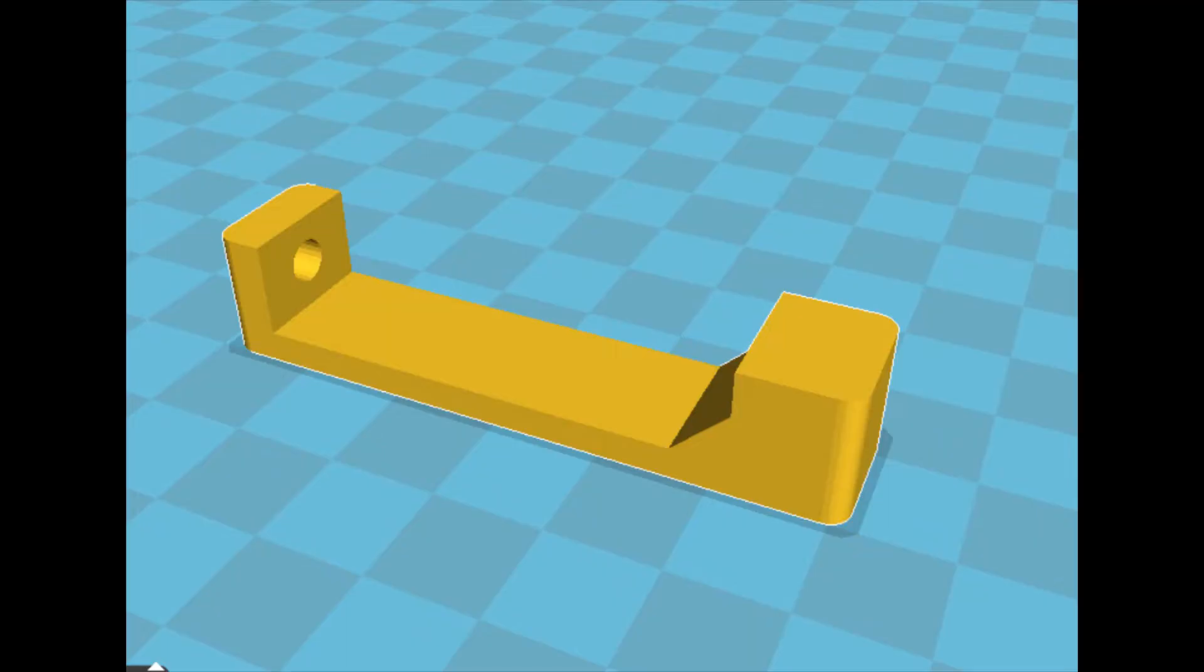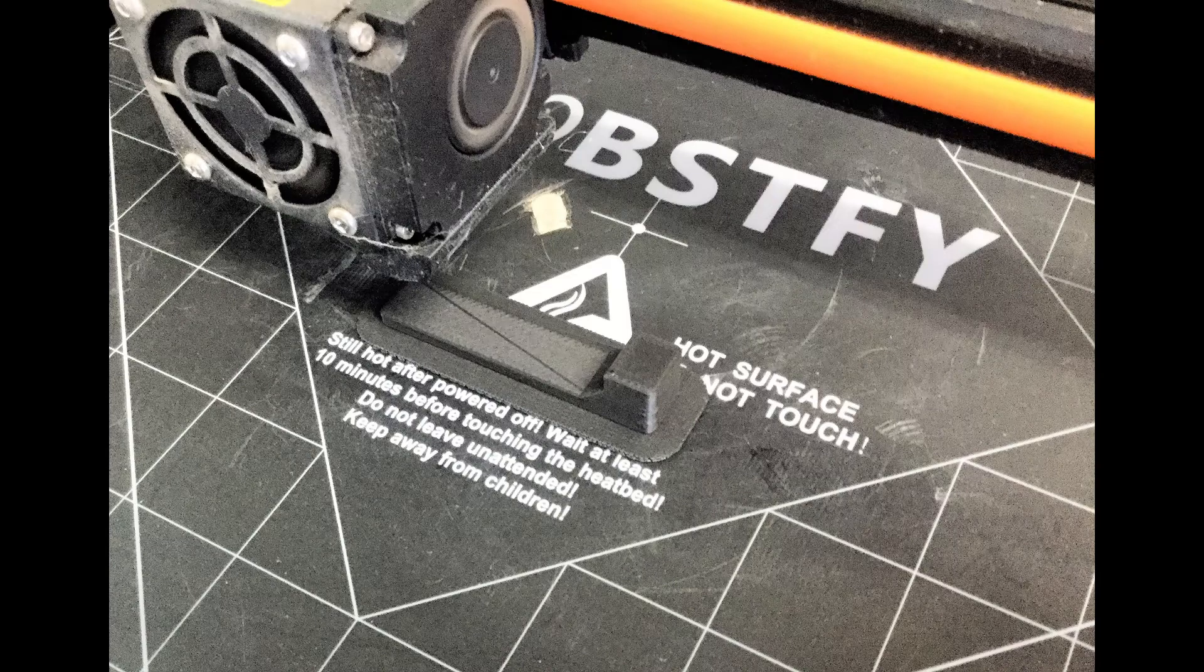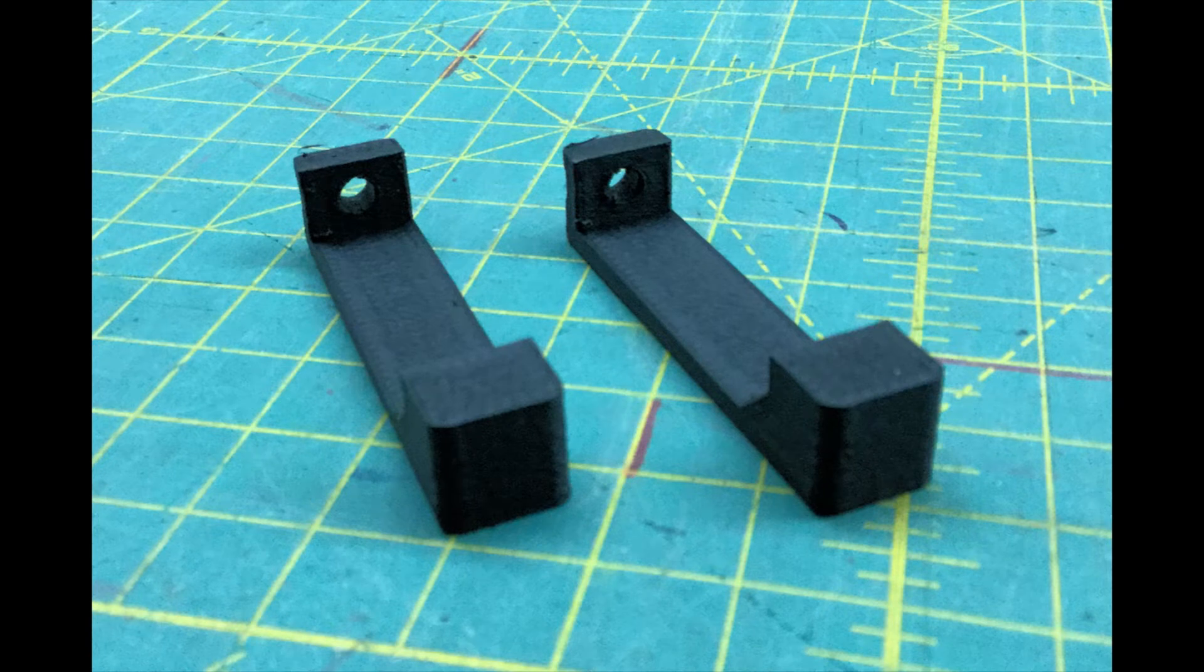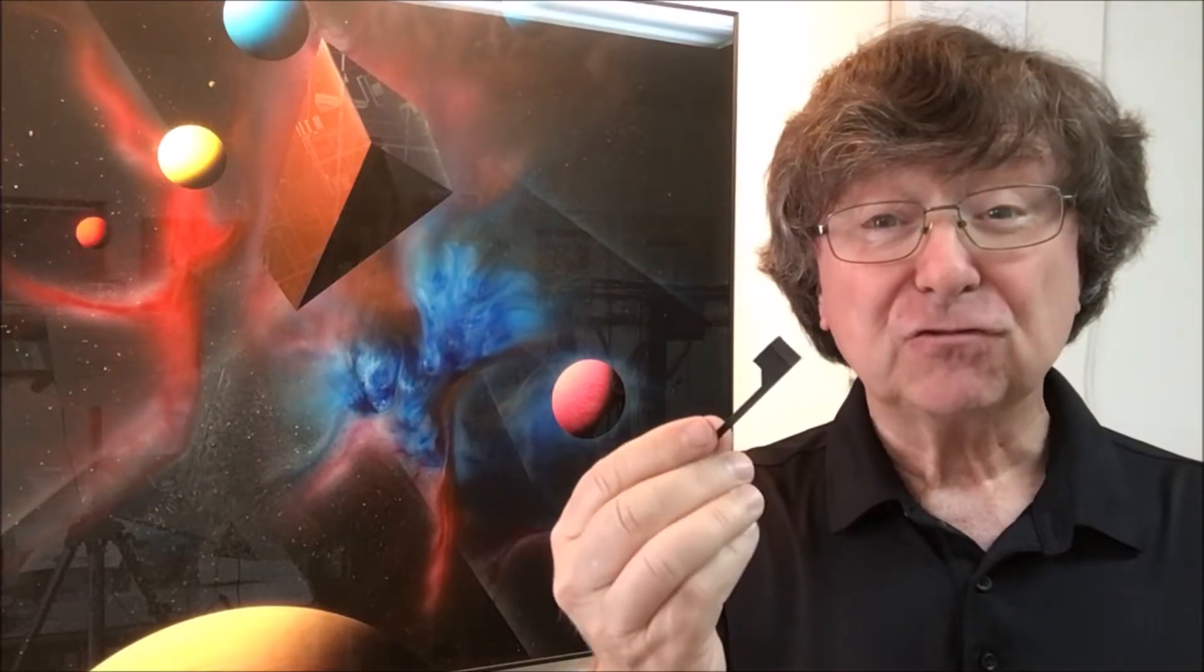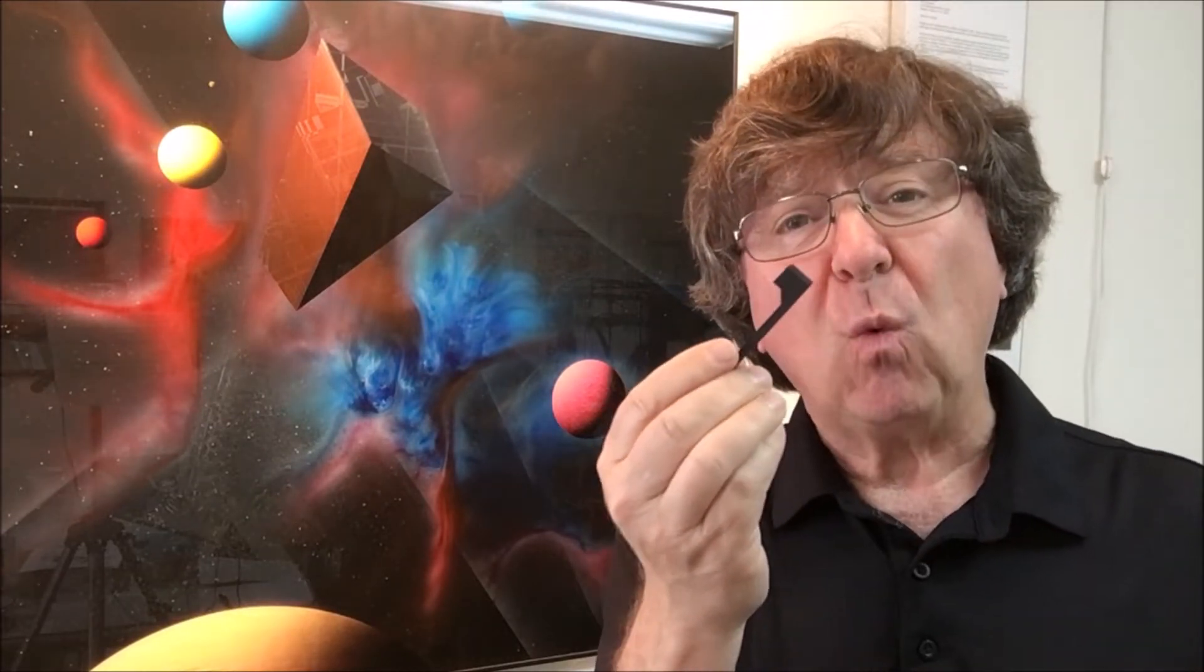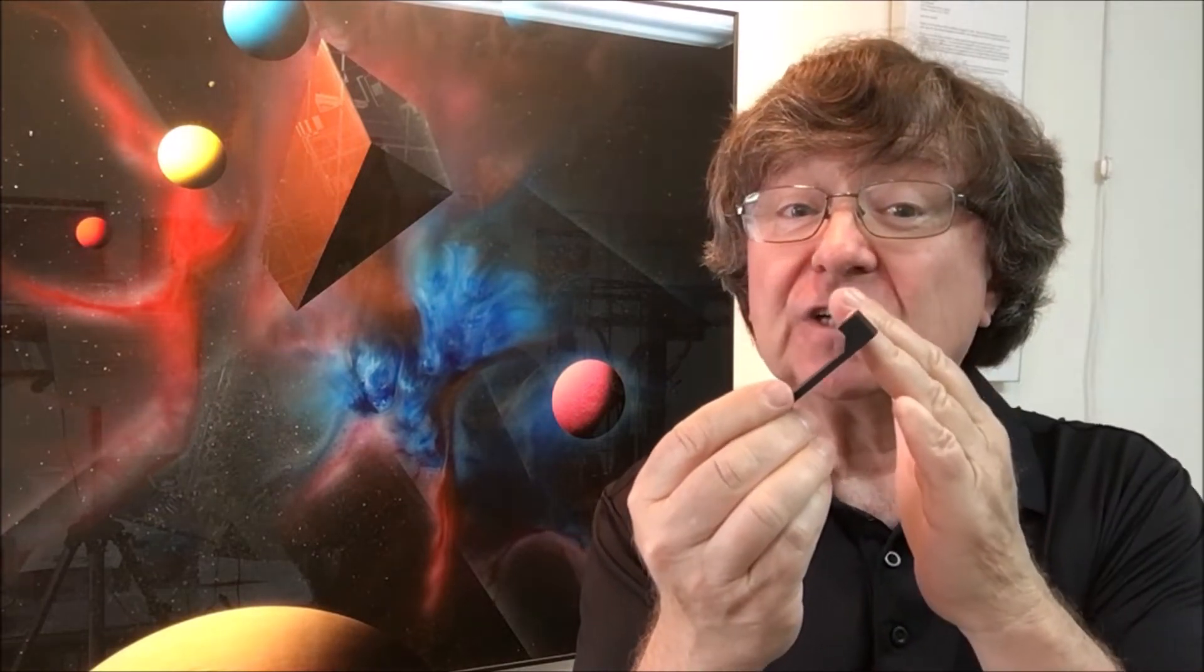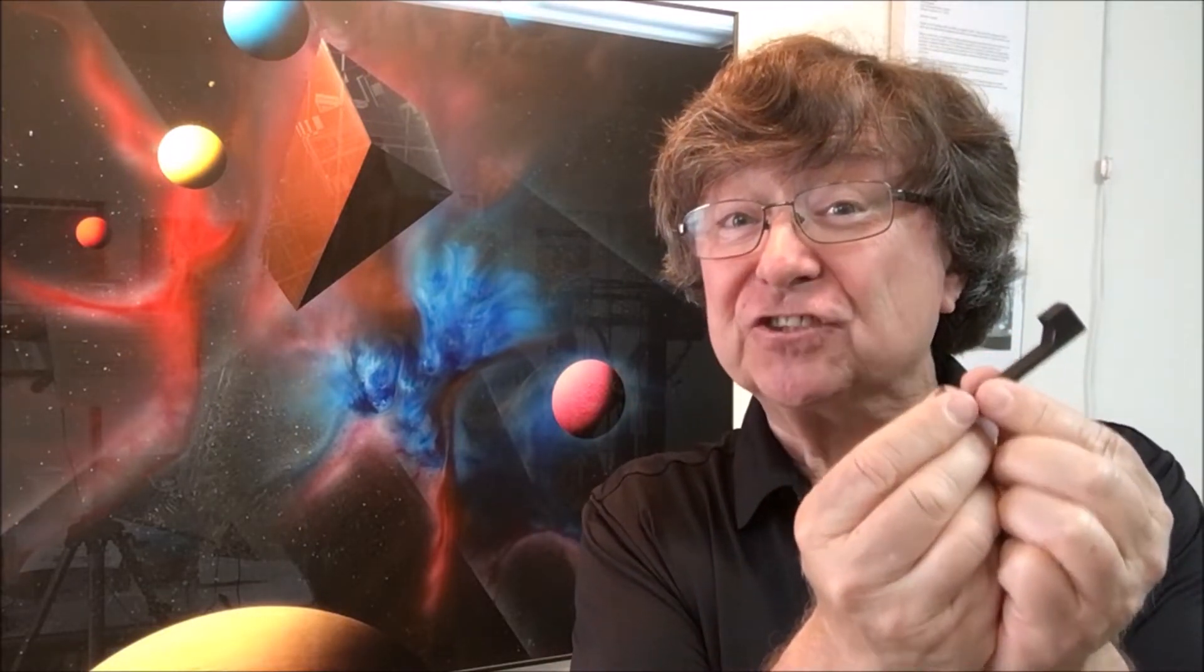These are 3D printed graphene electrodes. They are made from an electrically conductive material called graphene and PLA, a plant-based plastic used in 3D printers. The PLA melts easily and doesn't stand a chance against the high temperature inside the engine. Now the graphene electrode gets gunk on it too. However, the engine rapidly melts the face. While it's melting, the engine exhaust blows off the outer surface, exposing fresh conductive graphene below. We just continuously feed it in while the engine is running. At least, that's the idea.